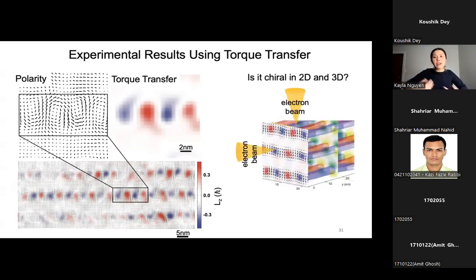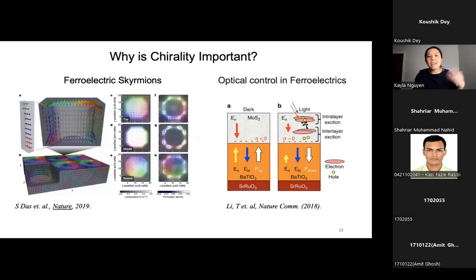Now the question is, is it three-dimensionally chiral? What we need to do is make a new sample, and instead of looking down the 0, 1, 0 direction, we need to look down the 0, 0, 1 direction to see what that structure looks like. So we need to look at it sideways. Why is chirality important? Chirality is important because we can learn how to tune our polarization structures with different chiralities of light, for example, left-handed or right-handed polarized light. And there are new emerging ferroelectric skyrmion structures that also have chirality. So it's important for us to utilize chirality and understand how chiral our sample is.